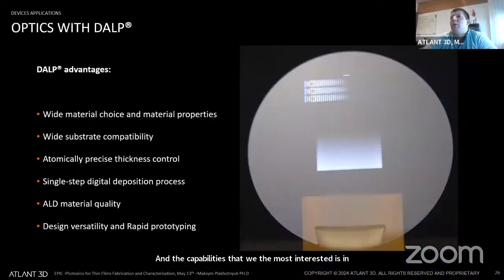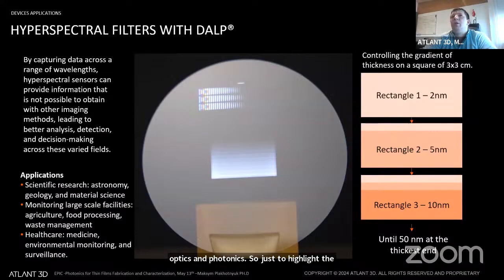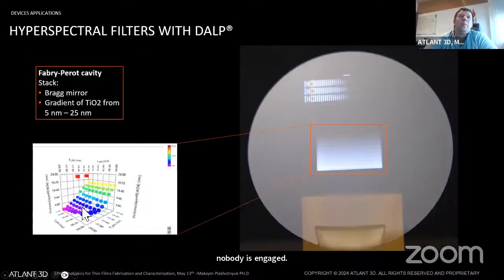So just to highlight the development that we did with the gradient thickness filter, this is how we did. We made bigger squares with one thickness, then we reduced the area for rastering to 5 nanometer thickness, 10 nanometers. We can really control it. It's like an overnight process where nobody is engaged. We just leave it and the machine does the work. And in the end, you could see here the control over the thickness. We did test measurements confirming what we wanted to achieve. We did this with titanium oxide, but it can be done with any type of material, including metals, or, like I say, there was a previous speaker interested in niobium oxide.